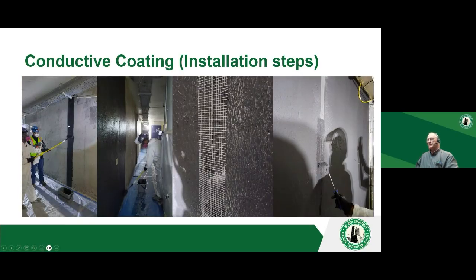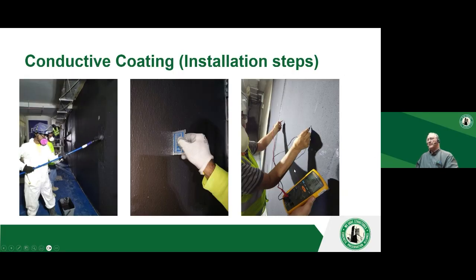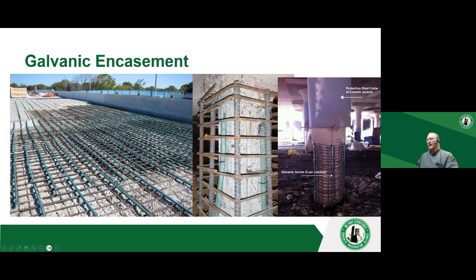Here's the installation. Put a layer of the coating down. You put the wire in that coating. You put a scrim over top of it. Then you coat over top the scrim. Then you coat the whole wall again. You check the thicknesses, and then you're checking continuity between your wire and the coating, and that's that. And it's really a good system.